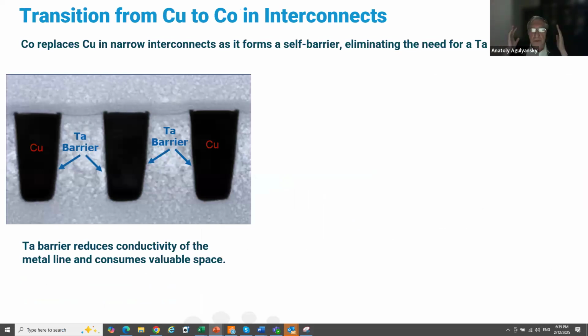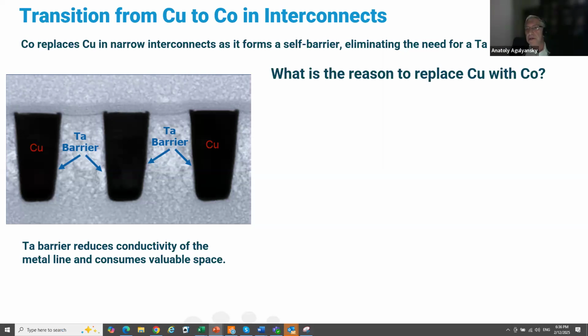We continue to make transistors smaller, smaller, and smaller. And what happened also, interconnection layers going perpendicular to this picture become smaller, but the thickness of the tantalum barrier remains the same because you should keep it in order to prevent diffusion. And the tantalum becomes very harmful because it takes volume, and tantalum is not a very good conductor. And one of the ways is to replace copper with cobalt.